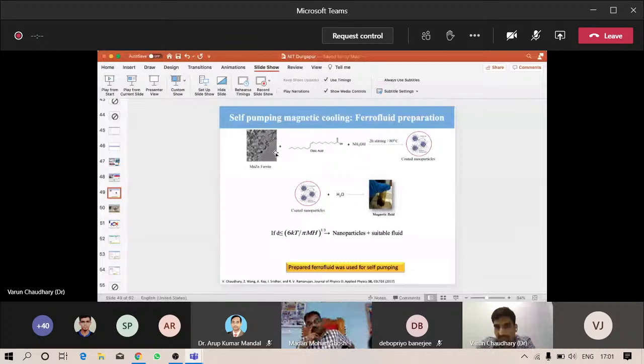So this first part is to prepare the particles and then coat them with oleic acid. Then we use ammonium hydroxide, with stirring at 80 degrees centigrade. Then these particles are coated with the oleic acid, and then we disperse them into the water. Oleic acid, is it the stabilizer used? Oleic acid with ammonium hydroxide. Yes, sir. Okay, so that is a stabilizer, right? Yes, sir.